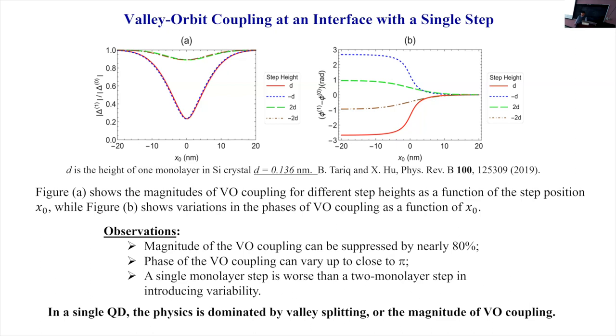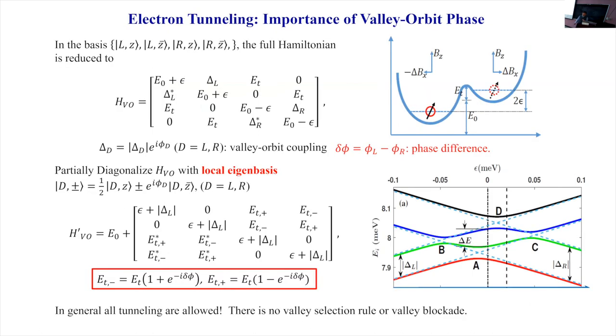If you only focus on the single dot physics. But when you go beyond the single dot, to a double quantum dot, the phase also comes into play, right? Because as I mentioned before, the valley orbit coupling is really sensitive to how the interface looks, the atomic detail of that interface. So that phase would depend on the details of that interface. Two quantum dots generally do not share exactly the same interface, and that means their phases, the value of the phase, could very well differ as well, right?